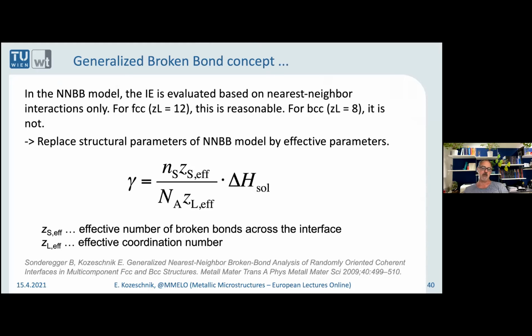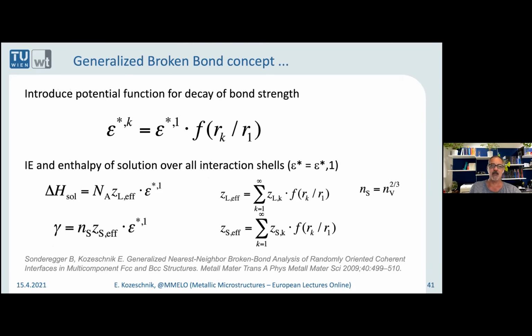So what we did was we went into some kind of numerical scheme, and we said, okay, we will count all bonds across the interface and infinitely large into the volume. And we replaced the number of broken bonds by effective numbers and effective coordination numbers. We have an energy for the first nearest neighbor, and the second, third, and fourth nearest neighbor will have a decreasing interaction energy with some kind of function. We actually used the Lennard-Jones potential, so 1 over r to the power of 6.